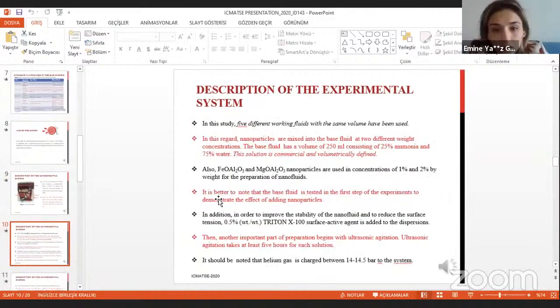So in this experimental system, we have 5 different working fluids: 1% magnesium oxide alumina spinel, 2% magnesium oxide alumina spinel, 1% iron oxide alumina spinel, and 2% iron oxide alumina spinel. So we have the base fluid, with a volume of 250 milliliters, consisting of 25% ammonia and 75% water. As mentioned, we have 1% and 2% nanoparticles. Firstly, we tested the base fluid as the first step of the experiments, and then we demonstrate the effect of adding particles.